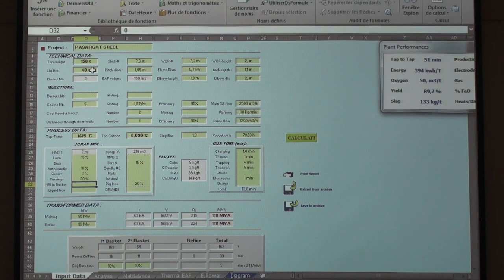Yeah, they say, but you said it is not a big energy saving. No, I mean, don't mix it up. Having hot heel allows you to have, let's say, higher power input at the beginning of the melting phase. So you can go fast in megawatts, avoiding refractory wear on the bottom. But too much, I don't see the necessity, because then you have more liquid steel to reheat. Except if you go to 40 or 50%, the area of the hot heel doesn't change so much, or the depth. It's anyway the furnace diameter. So you can increase there. There is no disadvantage anymore.